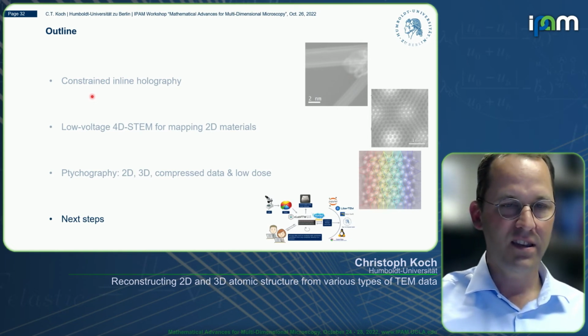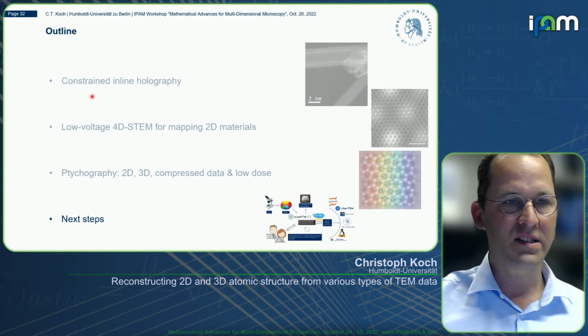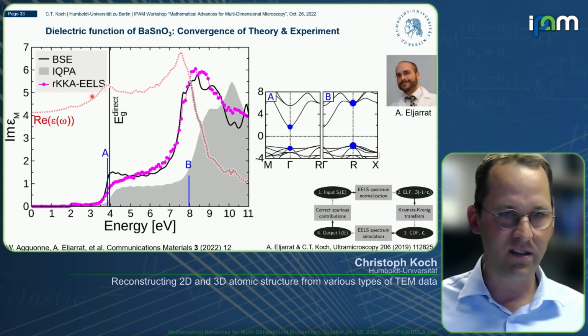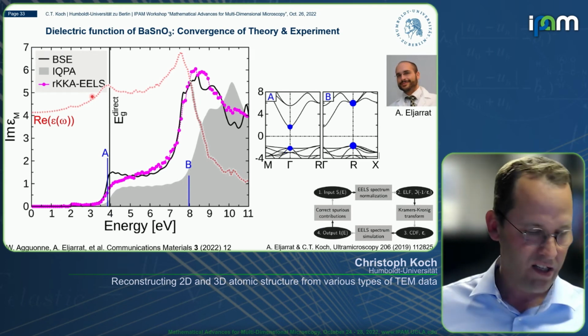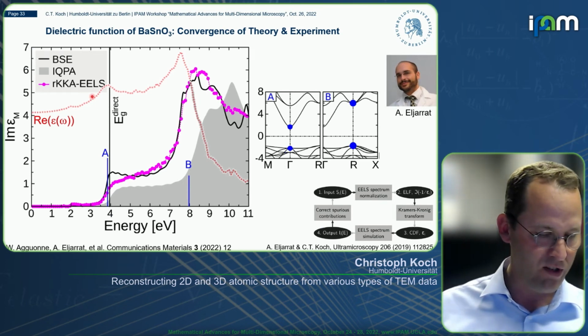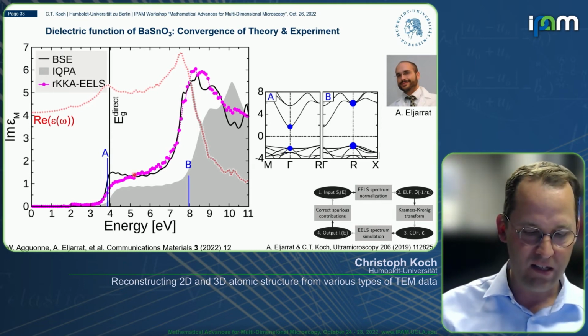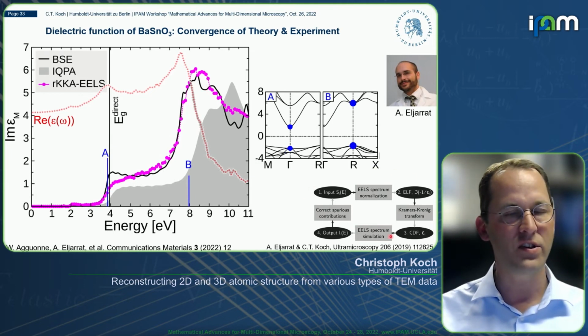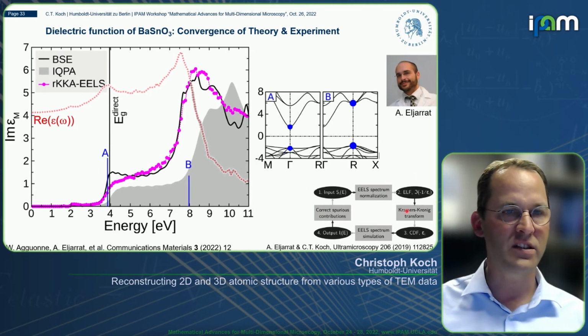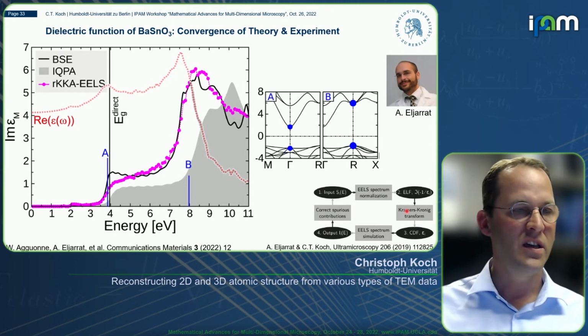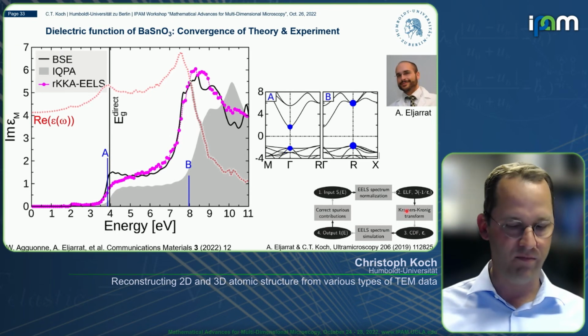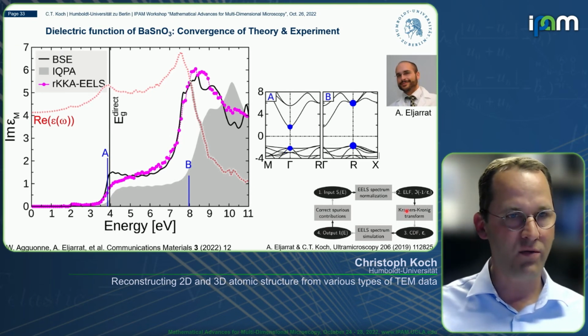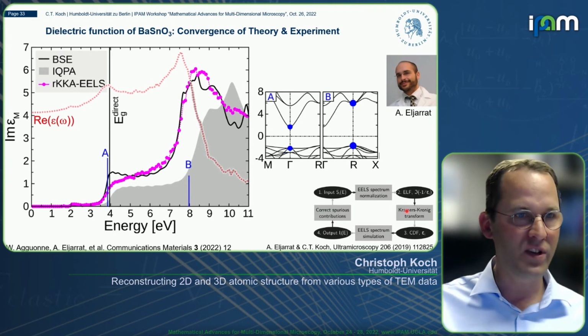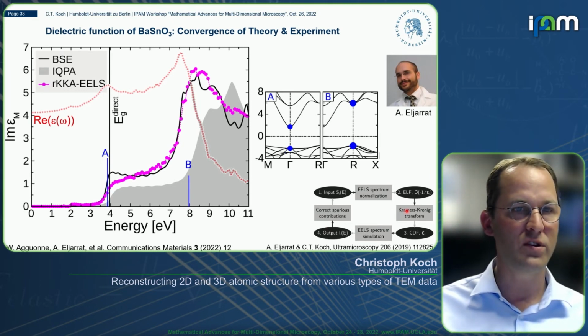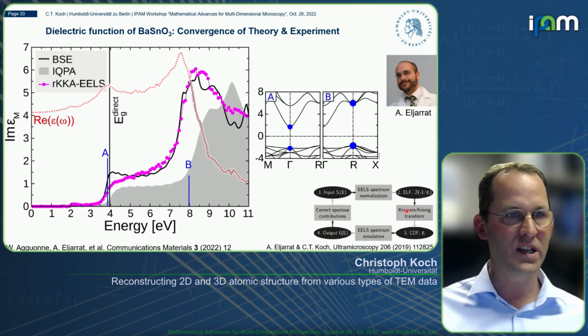And there is more behind it than just that, and I'll show you one example here. This is just a motivating example, not in ptychography or diffraction mapping, but in EELS. What you see here is the dielectric function, reconstructed using quite an elaborate Kramers-Kronig based reconstruction algorithm, which also takes into account relativistic effects. So it self-consistently corrects for things like Cherenkov radiation, guided light modes, and so on, that are all defined in the Kröger equation, but to actually get them out of the data you do have to do some iterative refinement. And if you want to apply this to mapping, it also needs to be GPU enhanced and so on.